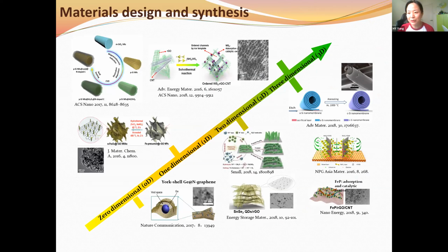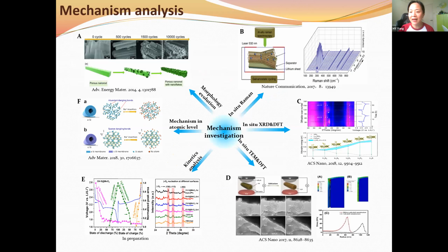My research group in SUTD is working on low-dimensional nanomaterials for lithium-ion batteries and battery systems beyond lithium-ion batteries. We are looking at nanoparticles, layered structures like graphene or graphene oxide, and three-dimensional structures: a combination of carbon nanotube, graphene oxide, graphene, and nanoparticles composited together. We have been working on the morphology evolution of the structure and its impact on capacities and cycle lifetimes, using in situ systems like in situ Raman and in situ XRD to generate in situ images when we charge and discharge the battery.